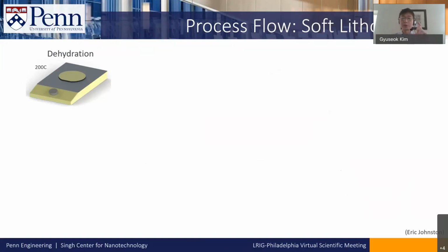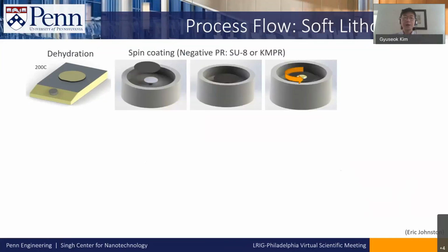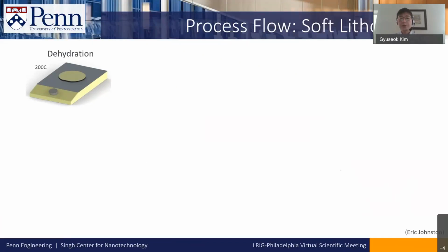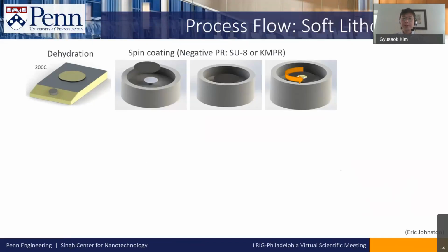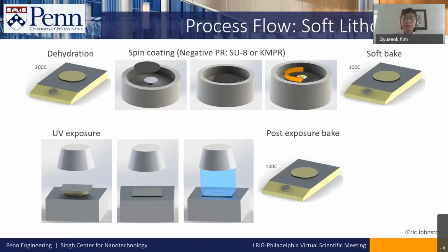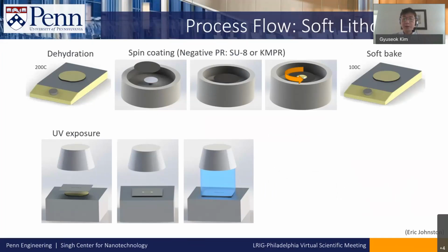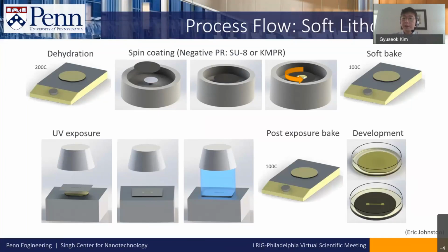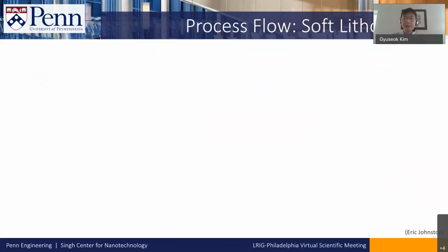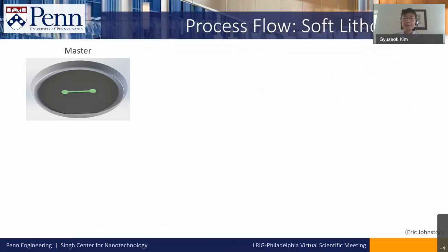So first, of course, we start with the silicon wafer. The first step is dehydration to improve the adhesion between the silicon wafer and the photoresist. And then we have to spin coat the negative resist. So we dispense either SU8 or KMPR, and then soft bake at 100 degrees Celsius and do the exposure. As you can remember, since we are using the negative resist, the exposed area will stay after the development. So before development, we have to do some post-exposure bake to finish up the chemical reaction. And then if you put the sample in the developer, any exposed area will stay on the wafer. And this is what we call the master. So now the master is prepared.